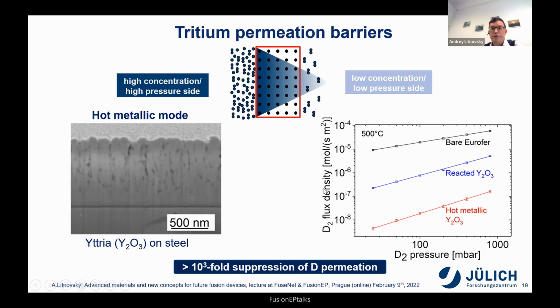And you can see here the attenuation. How efficient are we? How much do we suppress this deuterium flux? You can see it as a function of the pressure, actually up to the very high pressure of 1 bar, which is unrealistic for fusion, but for test purposes it is good, at 500 degrees C. The pure structural material Eurofer, a reduced-activation ferritic-martensitic steel, is already quite a good barrier, capturing almost everything: from 100,000 deuterium atoms only one comes through. But the permeation barriers, even the non-optimized, increase this at least 10 to 100-fold, whereas the optimized yttria can make again more than a 1,000-fold increase in the efficiency of tritium capturing in the plasma components. And this is during the regular plasma operation.